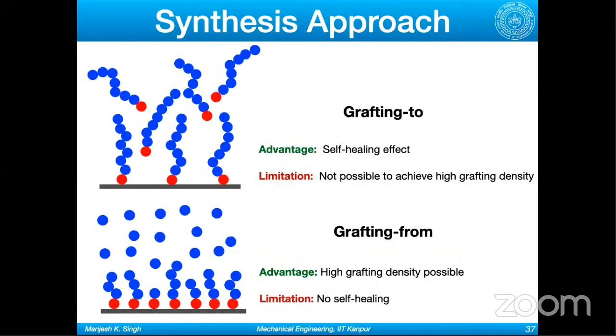So there are primarily two methods to prepare polymer brushes. One is grafting to, where you have polymer chains already in a solution. You pour it on the surface, like we used to do on the silica surface, and because of electrostatic interaction, it will get attached from the functionalized group and form a brush-like structure. The advantage here is the self-healing effect. Suppose you are rubbing your polymer grafted surface against something, and some polymer chains wear out. If you have prepared your polymer brush using the grafting to approach, there are other polymers in the solution freely roaming around, and they will come and replace them. So it will have a self-healing effect.